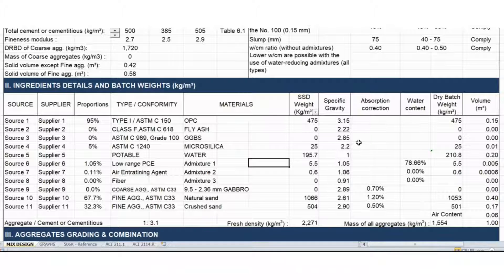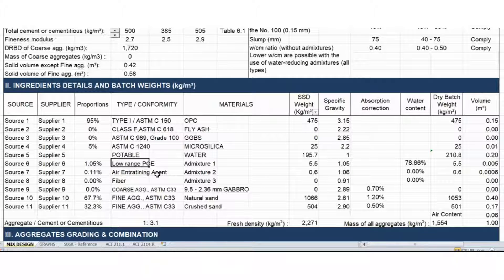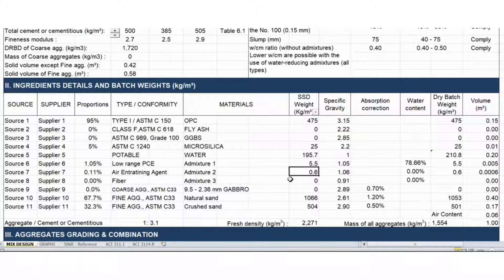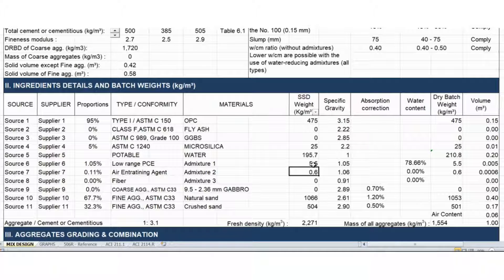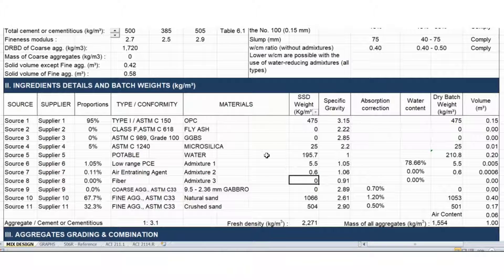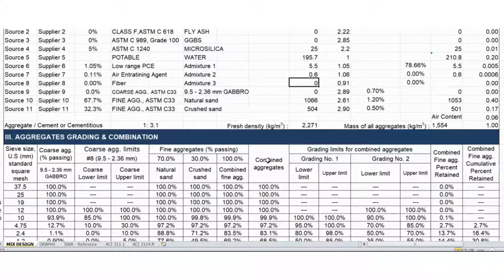Going forward, this is 95% OPC — these are the typical values in the table — and 5% micro silica. Normally we are using the new generation of PCE-based admixture and some air-entraining agent. We need air content in this case, as it will help reduce the rebound of aggregates and paste while doing the shotcrete. Sometimes you also use fiber depending on the specification.